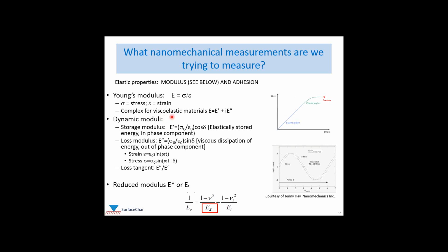Now the modulus is complex for viscoelastic materials. And viscoelastic materials are ones where their mechanical properties are rate dependent. So for those kinds of materials, we have to talk about dynamic moduli. And the dynamic moduli are the storage modulus, or the real component, which is the elastically stored energy, and the loss modulus, shown here, E double prime, which is the viscous dissipation of energy. So storage modulus is E prime, loss modulus is E double prime, and the loss tangent is the ratio of the two.